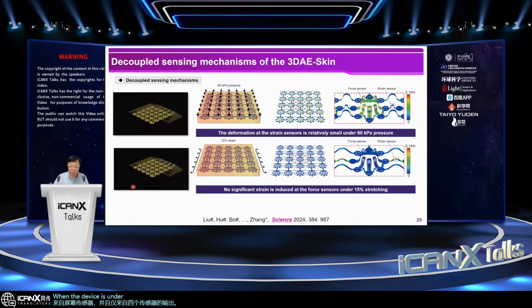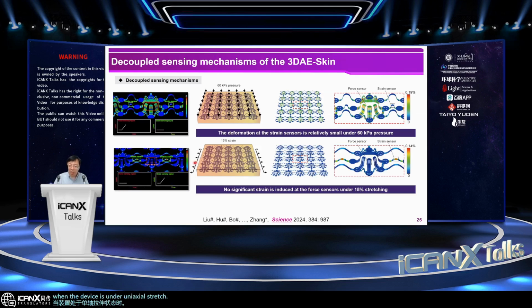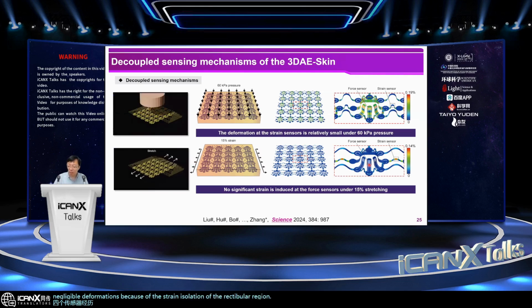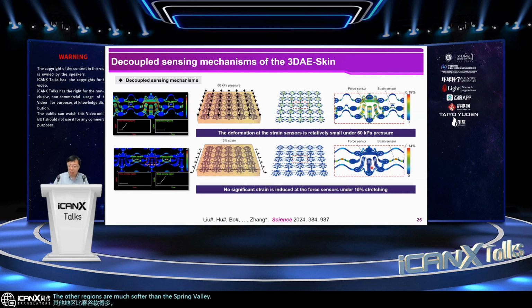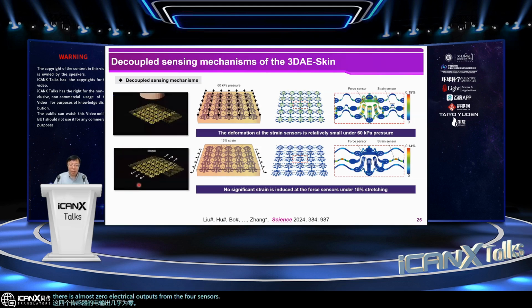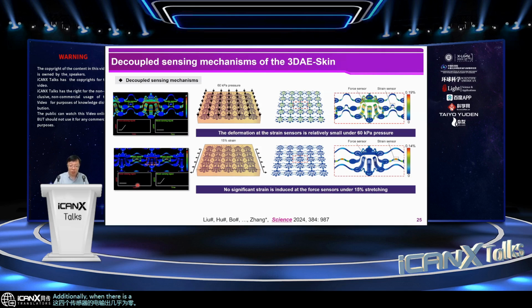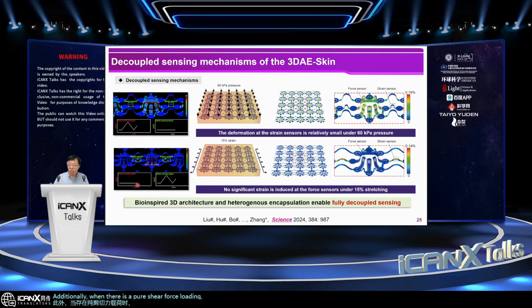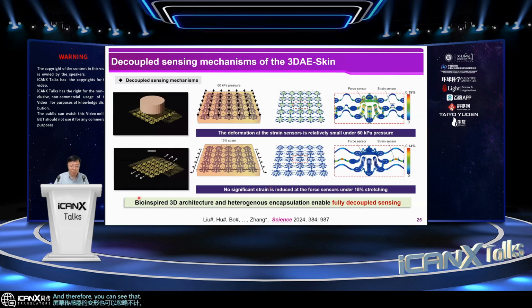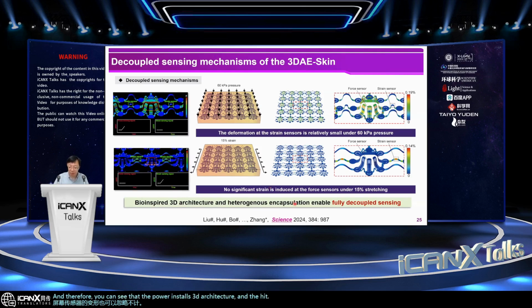When the device is under uniaxial stretching, the force sensors undergo negligible deformations because of the strain isolation of the relatively rigid cage mesostructure. The other regions are much softer than this region. Therefore, there is almost zero electrical output from the force sensors. Additionally, when there is a pure shear force loading, the deformations of the strain sensors are also negligible. Therefore, you can see that the 3D architecture and the heterogeneous encapsulation enable the fully decoupled sensing of this device.